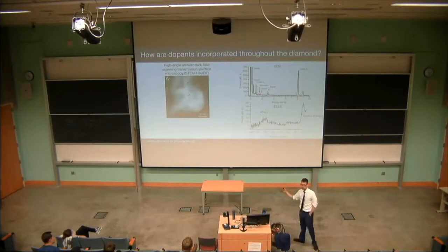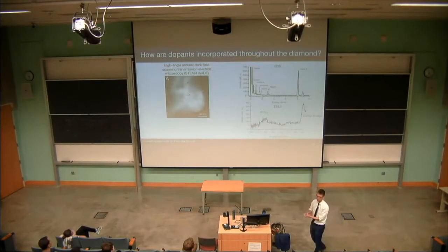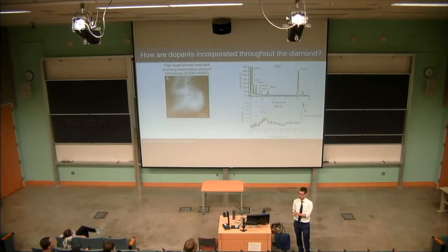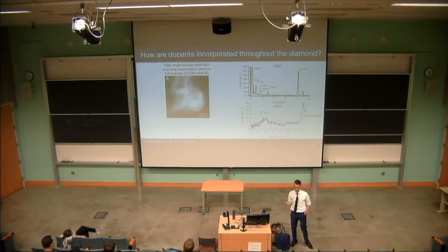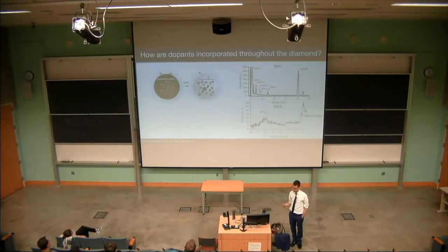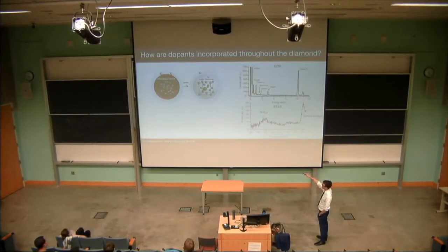But surprisingly, we also saw that there's argon in our material. Now, this isn't still loaded at pressure. This is material that we've taken out of the diamond anvil cell, that we've put on a TEM grid, actually flown to DC, and then put back under ultra-high vacuum. So there's no way that argon should still be sitting on the surface. Really, this indicates there's some argon that is trapped within the diamond lattice, and presumably inducing some strain on the material. It can't just be sitting there innocently. And we can also observe this in the EELS spectrum. So it's very clear we have multiple data points that there's argon trapped in the lattice, which means that perhaps the overall picture looks more like this, which is that we start with some kind of doped amorphous carbon material.